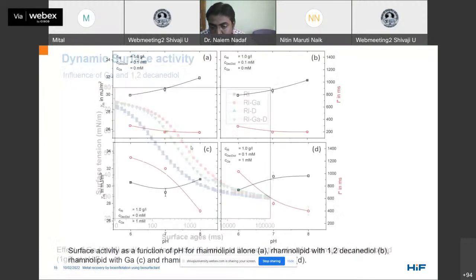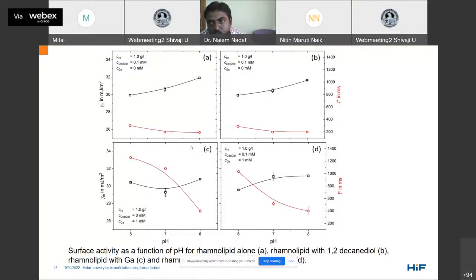Again, explaining these results in terms of gamma value and t star value, we can see that the diffusion coefficient for rhamnolipid alone and with 1,2-decanediol are nearly the same. Whereas for those with gallium alone or with gallium and 1,2-decanediol, the t star values are higher, suggesting that the complexes are taking more time to reach the interface. So this was all related to surface activity or aggregation.